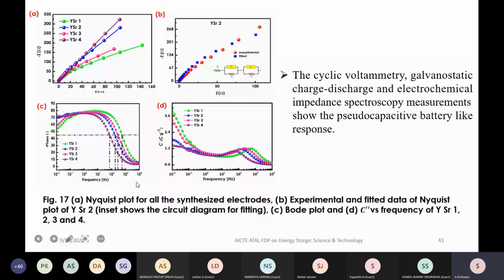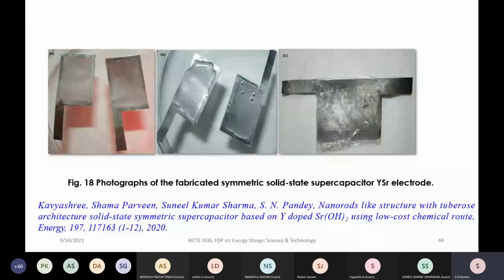The cyclic voltammetric, galvanostatic charge discharge, and electrochemical impedance spectroscopy measurements show the pseudocapacitive battery-like response. So after developing this, increasing the specific capacity and the cycle stability, we move forward to make the device. We cut this one in two L-shaped pieces, and then join them together to form this device. This is the actual photograph of the fabricated symmetric solid state supercapacitor YSR electrode. Why is it symmetric? Because both the electrodes are made of the same type.